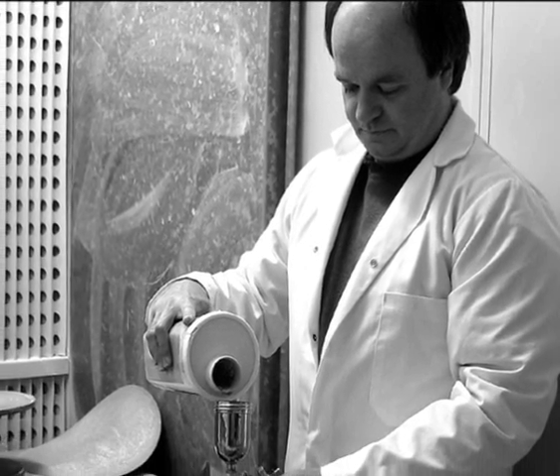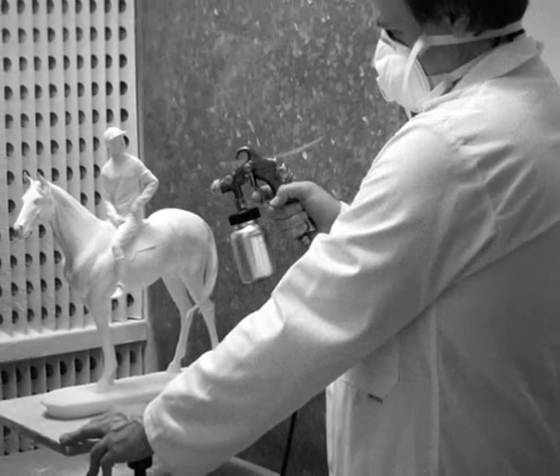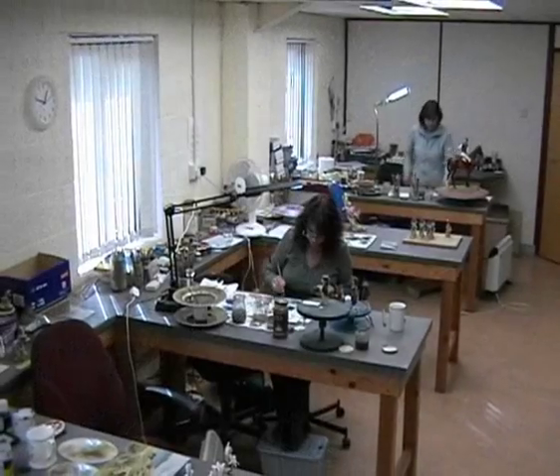Following the removal of the props, the model was glazed with a borosilicate glass coating, fired to reach a temperature of 1060 degrees centigrade over an 18-hour cycle.